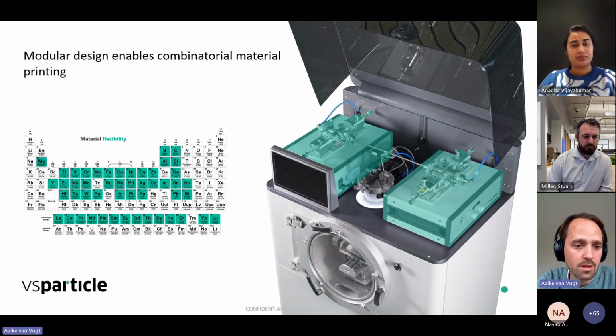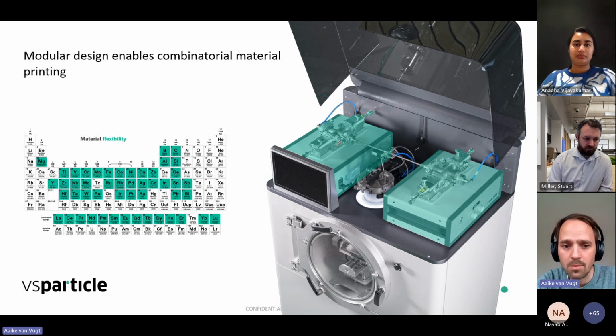And this gives us the capability to process so many different materials because all those materials will evaporate at such a high plasma temperature. And that also makes the system very useful because the processing is almost the same if you want to process gold, titanium, platinum, carbon. There's little difference in switching between those materials, which is something that is a big problem in chemistry. If you want to make gold nanoparticles, you have a completely different chemical recipe that you need to follow and optimize versus if you want to make a palladium nanoparticle. And sometimes you can't make your particle because the chemistry doesn't allow you to do it.